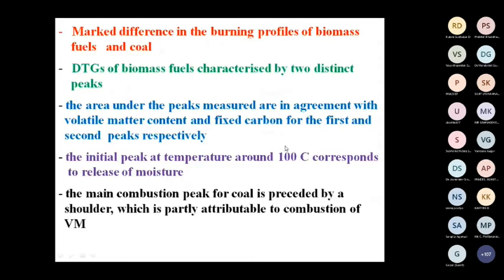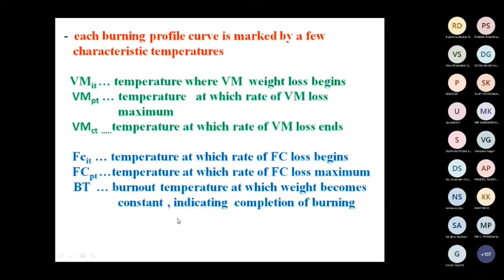So this is the thermogravimetric analysis of the biomass fuel, from which each burning profile curve is marked by a few characteristic temperatures. You can study the burning profile in a more elaborate manner. Each burning profile curve is marked by a few characteristics. First, VMIT, the temperature at which volatile matter weight loss begins, the initiation temperature for volatile matter weight loss. Then VMPT, the temperature of maximum rate of weight loss. Then the temperature at which the rate of VM loss ends.